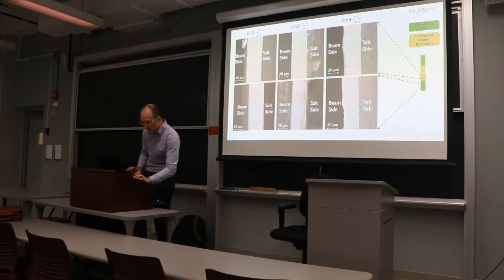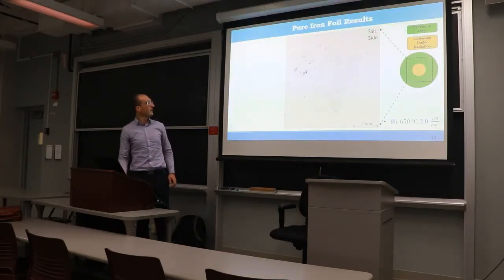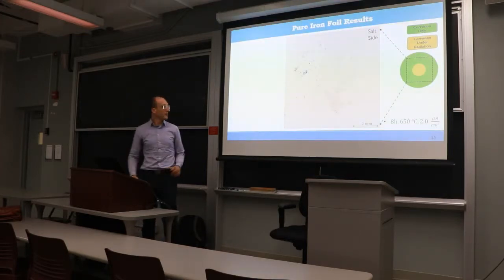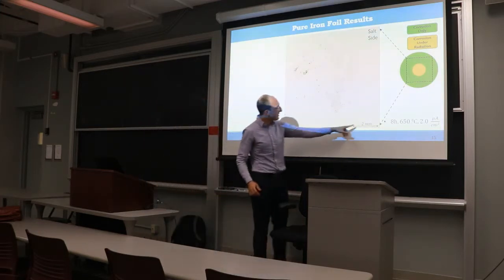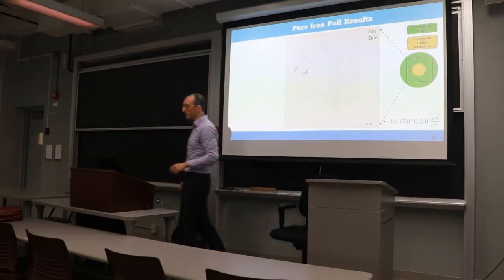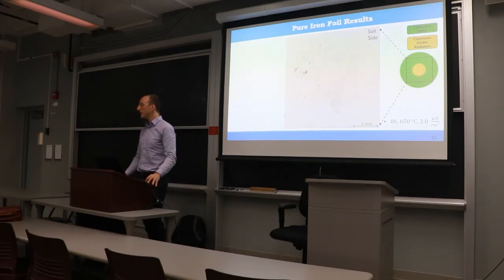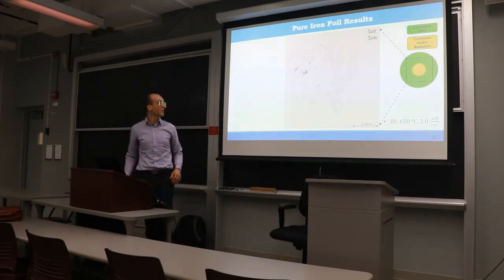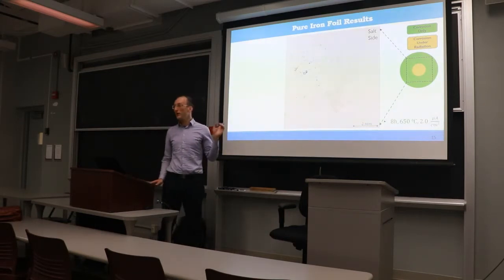So this is what we ended up getting. This is a pure iron foil. And what you're seeing here, that scale bar is not an error. This is a composite of many thousands of images in the SEM. We wanted to get an SEM image of the entire foil. And this was pure iron.